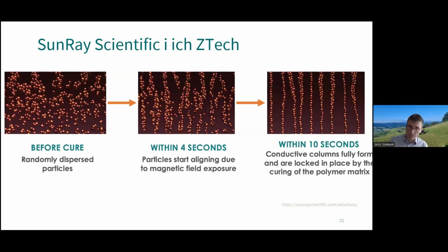And going back, there's a lot going on within the adhesives. Concerning the electrical and mechanical parameters, it is worth mentioning one of the most interesting approaches that appeared on the market about a year, maybe a year and a half ago. It's the ZTech adhesive by SunRay Scientific. The main idea here is that they use a special magnetic field of their design during the curing process, which aligns metal particles in the joint. The conductivity is comparable with the best adhesives on the market. Mechanical properties are higher, mainly due to the high percentage of polymer within the adhesive.